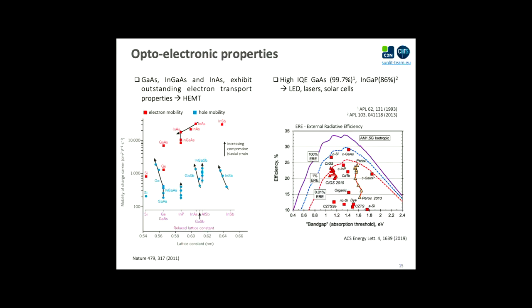From the electrical viewpoint, they feature extremely high carrier mobility. This is the plot of mobility for electrons and holes for different kinds of III-V semiconductor materials versus the lattice constant. You see also here you have silicon and germanium. They are a few orders of magnitude lower. They also have a direct band gap, although silicon has an indirect band gap, and a relatively high optical absorption coefficient. Here, for example, gallium arsenide is not a step function, but it's not that far, let's say.